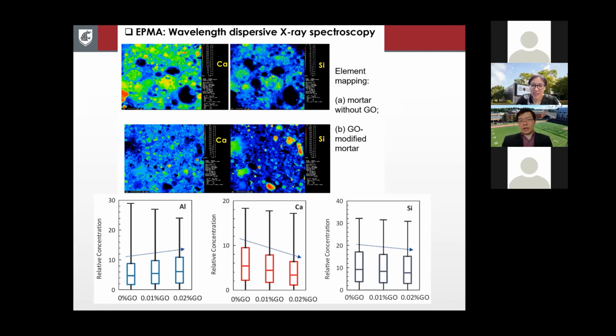Now, for cost, graphene oxide used to be very expensive. You could be talking about $50 per gram when this work barely started 10 years ago. But now, over the last 10 years, you can get this kind of graphene oxide for about $2 per gram. Again, this cost will further drop if we demonstrate and implement bulk applications, like graphene oxide in asphalt, in coating, in concrete or geopolymer. Because the raw material is graphite, it's abundant, and the process is very simple. Advances are made every week in the published domain. But the real issue is people haven't used this material in those bulk applications.